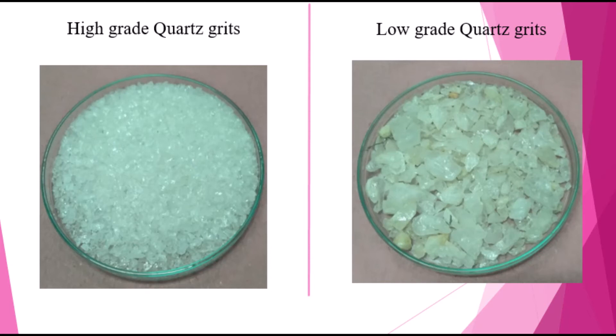After crushing the grit to powder, we have to remove all the total quantity of iron using a high strength magnetic separator. This is not a one-step process — we have to fix high intensity magnetic separators at relevant places. We will discuss the quartz plant later and see where to fix the high intensity magnetic separator.